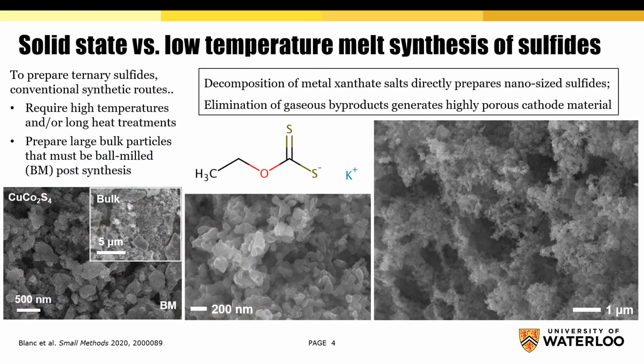The sulfide-based materials that are promising candidates for magnesium cathodes are typically prepared using solid-state synthetic routes that require high temperatures and long heat treatments and prepare large bulk particles that can be tens of microns in diameter. This particle size can be reduced post-synthesis through ball milling, but this process can introduce surface defects that can negatively impact electrochemical performance later on.